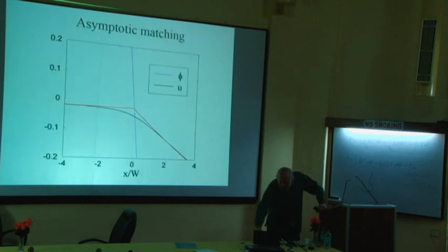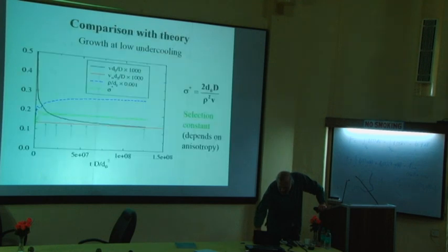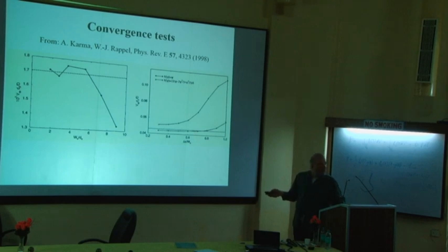And so the plot that I have shown you at the end was again extracted from this historical paper. They calculated the dendrite in 2D, and what you see here is the characteristic plot that you should always seek if you want to assess the quality of a phase field model. Here are various values of the interface thickness. So this is a test of what dendrite tip speed you get for different interface thicknesses.